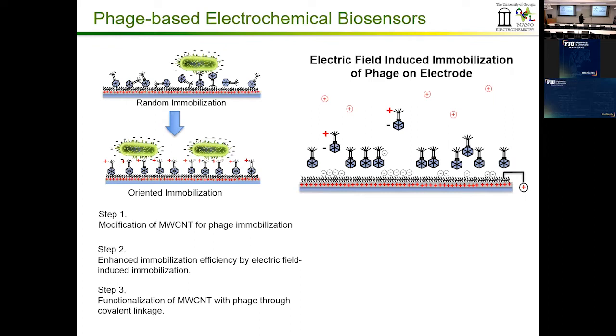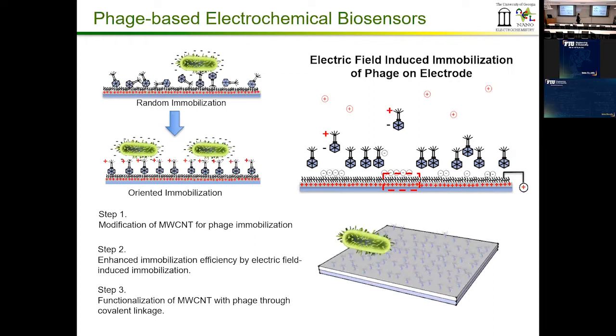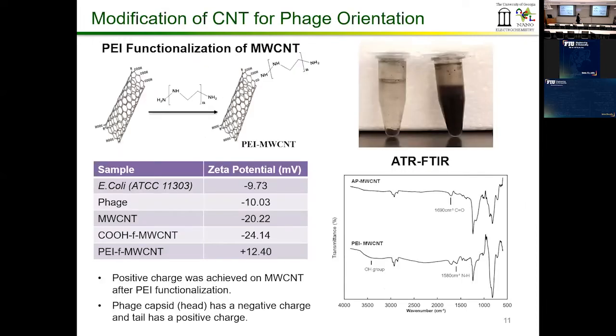the surface. The way that it has been done is the carbon nanotubes were modified with PEI, which is positively charged, and then the virus itself is negatively charged, but the head is negatively charged and the tail is positively charged. So when you apply an electric field and you have positively charged carbon nanotubes, there is a tendency for the head of the virus to get aligned towards the positively charged PEI. So we're actually using a charge-based immobilization strategy here. So that way you'll have an attack. These are all the viruses. You'll have an attachment of the bacteria onto the electrode surface.